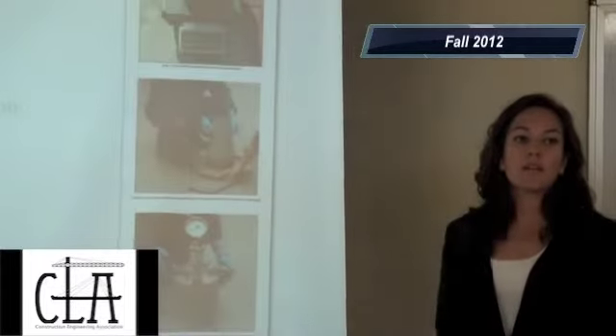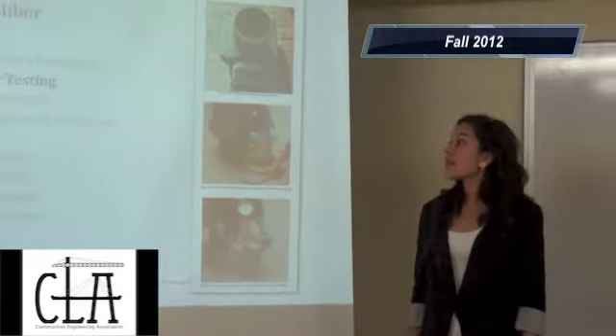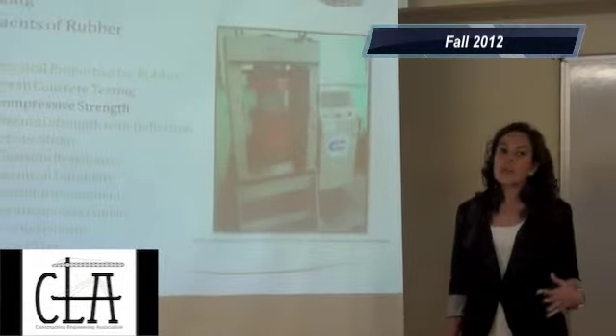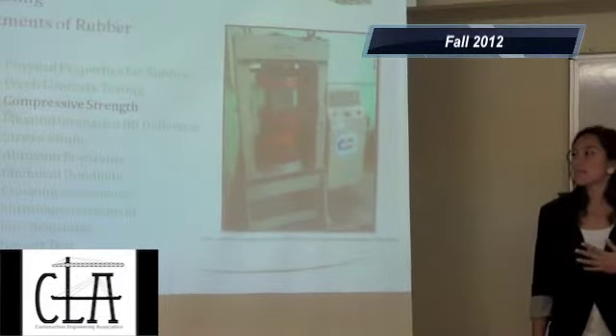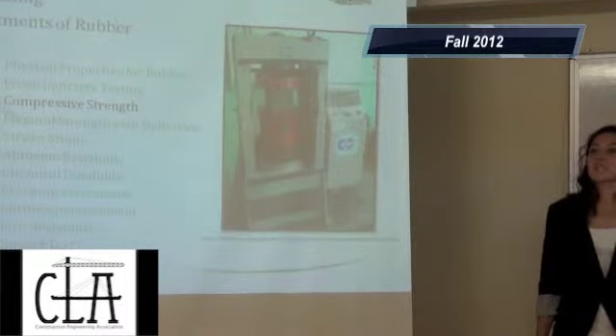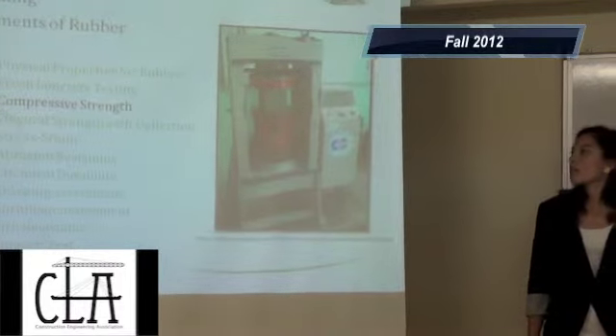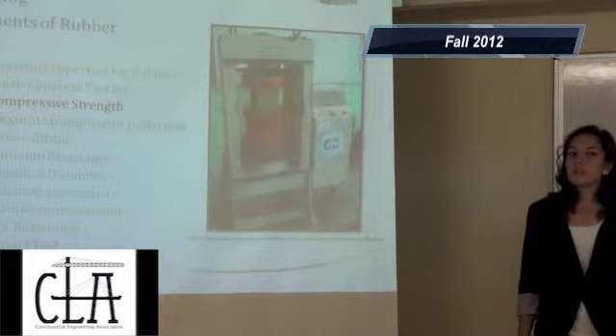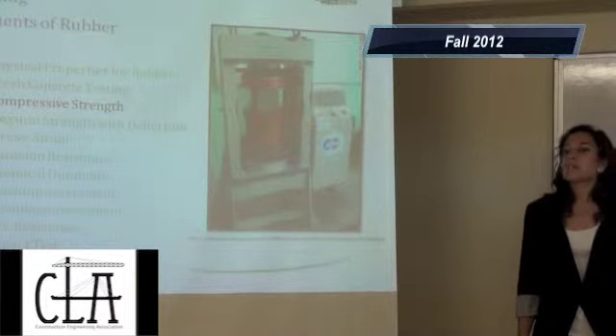Fresh concrete testing will involve the slump, unit weight, and air content of the concrete. We'll also be conducting the usual tests like compressive strength after 3, 7, 28, and 56 days, and the flexural strength with the deflection after 7 and 28 days.